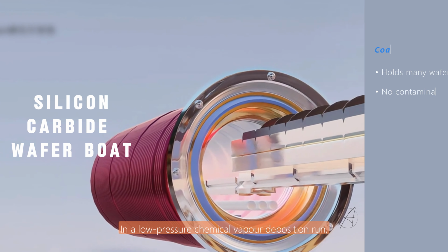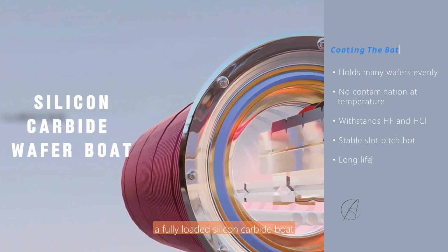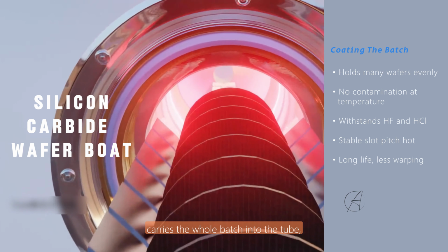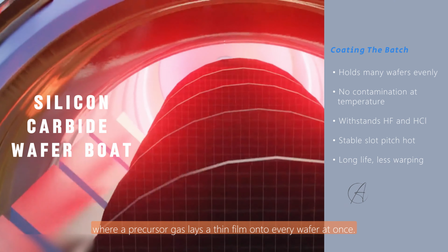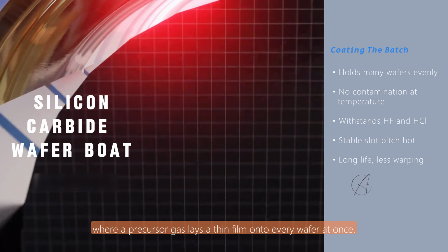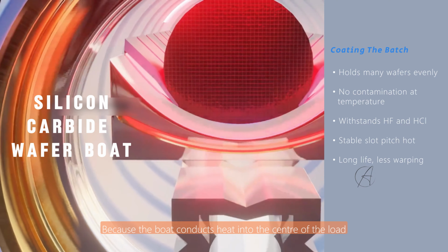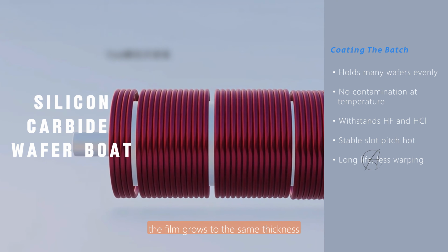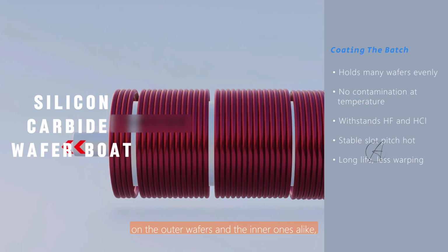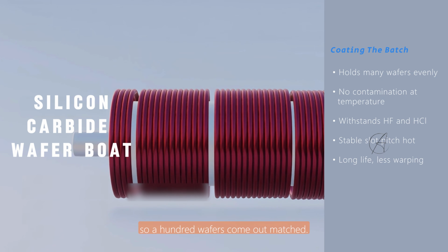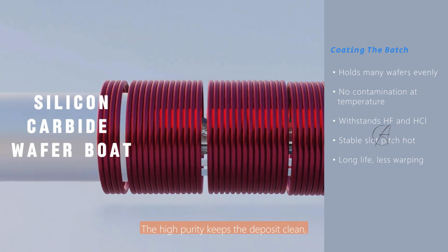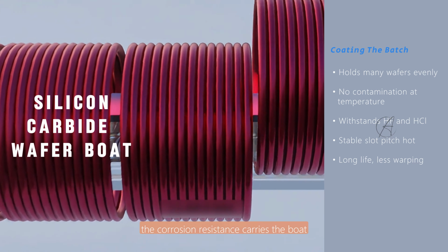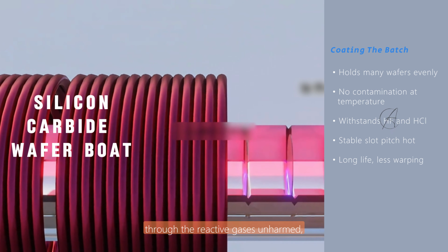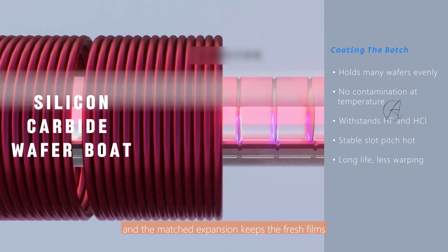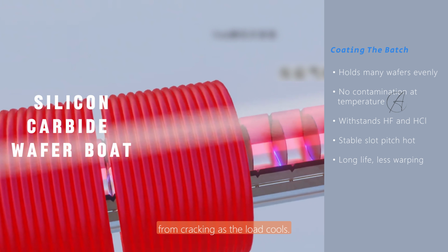In a low-pressure chemical vapor deposition run, a fully loaded silicon carbide boat carries the whole batch into the tube, where a precursor gas lays a thin film onto every wafer at once. Because the boat conducts heat into the center of the load and holds each slot at its set pitch, the film grows to the same thickness on the outer wafers and the inner ones alike, so 100 wafers come out matched. The high purity keeps the deposit clean, the corrosion resistance carries the boat through the reactive gases unharmed, and the matched expansion keeps the fresh films from cracking as the load cools.